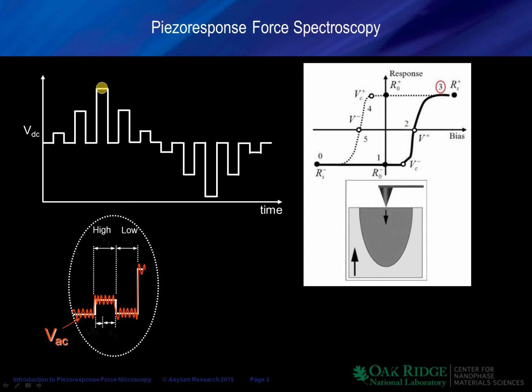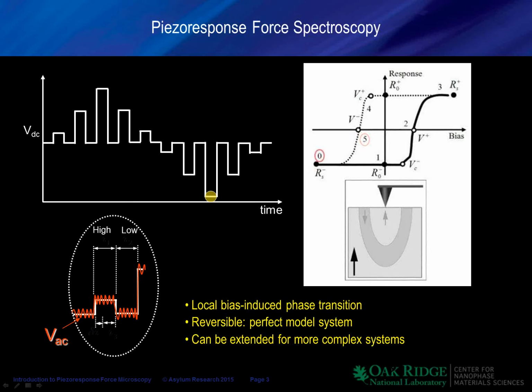If we keep increasing the bias on the tip, the domain will continue growing, and at some point the domain would be larger than our probing volume in PFM, then our response saturates. If we go in the opposite direction, typically nothing happens until we change the polarity of the bias, and then we start to nucleate and grow the domain with the opposite polarity, almost like a Russian doll. And if we repeat this process, we basically start to see the hysteresis loop.